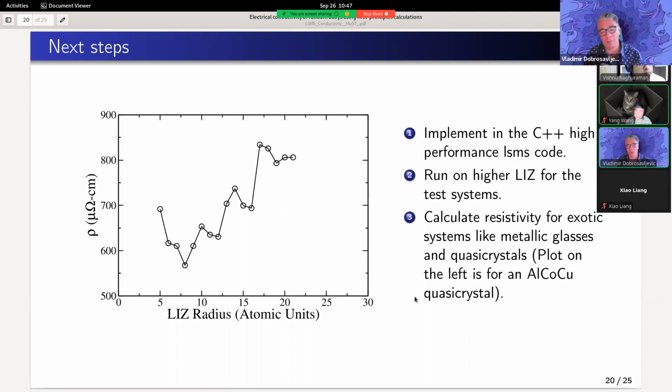In fact, in quasi-crystals, if you go to finite temperature, you can actually increase the temperature and reduce the resistivity in some cases, which was claimed to be strange. But it is consistent with the idea that multiple scattering processes increase the resistivity, and once you suppress them by finite temperature fluctuations, you can reduce the resistivity.